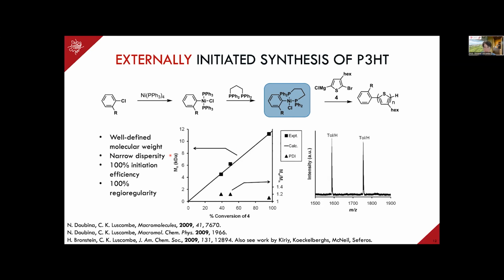There's other advantages in the polymerization that we developed, which is that we end up with very narrow molecular weight distributions or dispersities. So an ideal system would have a dispersity of 1. In this polymerization, we get about 1.1, 1.2, which is not bad.